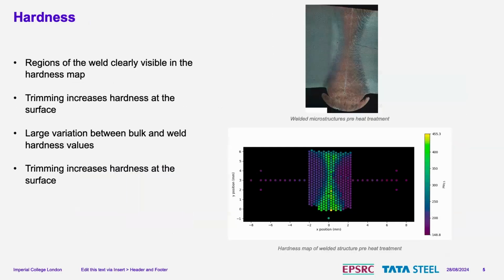Moving on. So in order to start determining how the fatigue life is going to be affected, I started with some simple mechanical tests. The first one was hardness testing. And so up here, we now have a post-weld but non-heat-treated sample. You can see we've got quite a lot of recrystallization into the martensite phase within the weld region. And you can also see the weld line going up the middle. We then, after the recrystallization zone, have the thermomechanical zone and the heat affected zone.